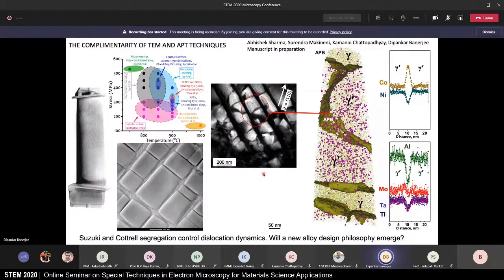So what we have is a situation that we could not imagine even 5 years back, but which has evolved with this combination of HAADF and atom probe tomography to image Suzuki and Cottrell segregation during the shearing process under creep in these structures. And essentially such segregation, we now understand, controls dislocation dynamics. And let me emphasize again, this could not have been understood or even characterized without this complementarity of TEM and atom probe tomography techniques. And so the question in terms of engineering is that this really leads to a new alloy design philosophy. Earlier alloy design philosophies focused on just the size, the misfit, the volume fraction of these precipitates. And now we have to worry about segregation and segregation-driven dislocation dynamics which control plasticity in these materials.